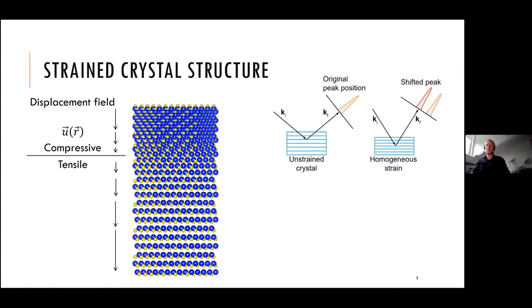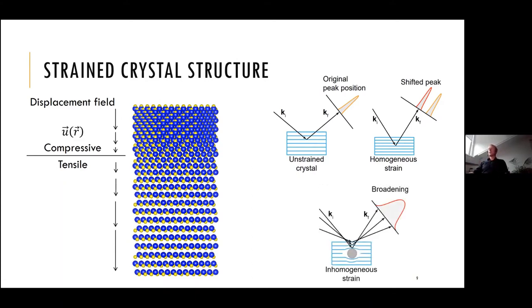By shining X-rays on this type of structure, we can get different effects from the simple point of view. If the crystal is unstrained, we get just the original position, which can be found from crystallographic techniques in the literature. If there is a homogeneous strain inside the structure, the peak will just shift in the Q space, showing that atoms get either closer or further apart. If you have an inhomogeneous strain, for whatever reason, the peak starts to broaden or change its shape, and it can become asymmetric. And this is the most interesting part, that we can actually look into this inhomogeneity of the crystalline structure, caused by lots of different effects.